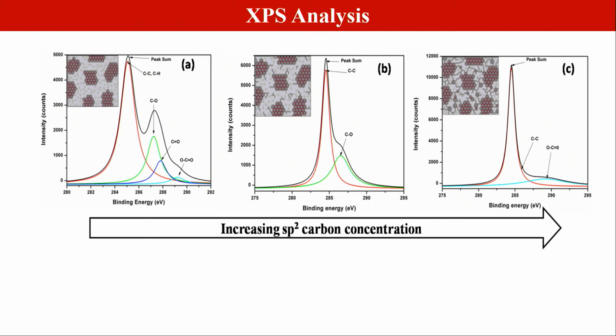So, there is a competition between the two, and you can see here the carbon-carbon bonds and the carbon-oxygen bonds. Carbon-oxygen bonds get reduced with the reduction process as a function of time. And finally, we are getting almost 80 to 20, but this structure is very important as I see. These are the graphene structures that we have regenerated in this reduction process.